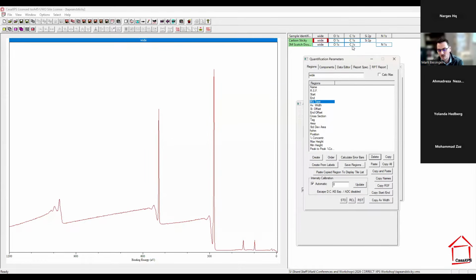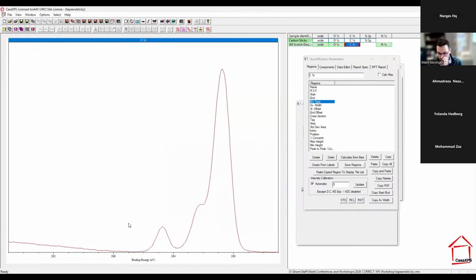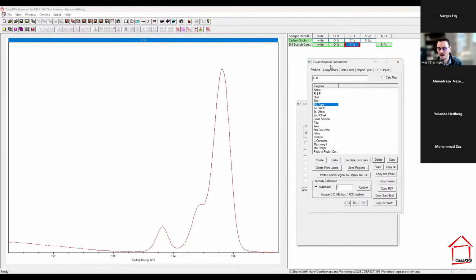And usually when you reach that steady state, you've pushed it down, so the apparent binding energy is down a little bit for all elements. And so we need to do what's called charge correction. If we look at something like carbon 1s, the aliphatic peak for carbon is a common charge correction reference. Again, we'll talk a lot about that later, but I want to go through and do a quick curve fitting of the carbon 1s peak to show you how we go through that process.